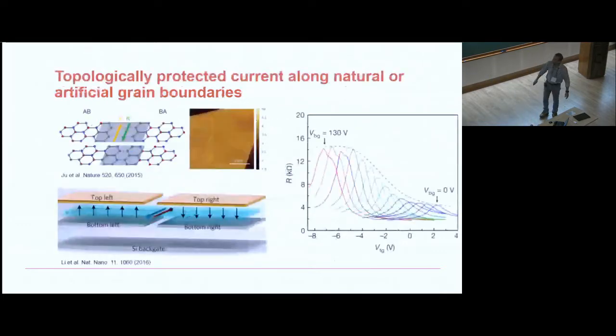Okay. There are many other experiments which actually showed similar behavior happening at graphene grain boundaries. Bilayer graphene grain boundaries are very interesting because you are changing the stacking of A and B, and that will lead to a change in the topological invariant, and that will lead to very large, beautiful non-dissipative flow along the grain boundaries, and that has been already observed by several groups.